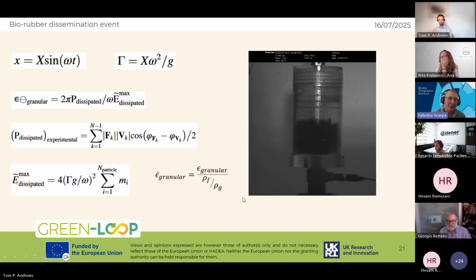the granular damper that you see over there is the one made with recycled rubber particles. They are roughly over 2.5 millimeter of diameter, and it has the same volume fraction as the previous damper that I showed you before. Now, already the behavior of the two is quite different, and the particle damper with rubber actually provides a better elastic response and creates also better visual fluidization, especially at low frequencies. If you can go to the next slide.